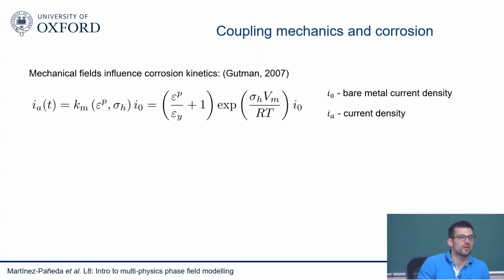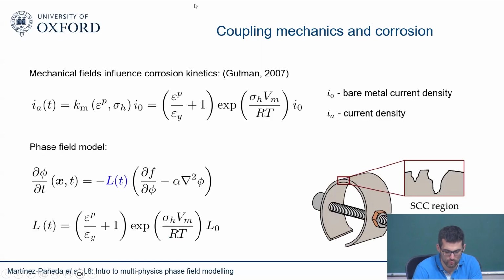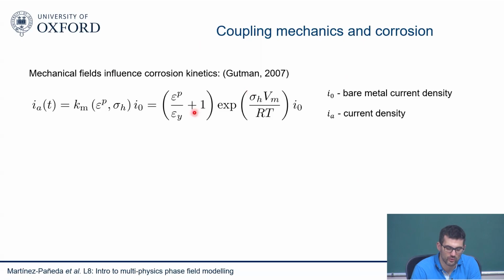But the idea is that corrosion kinetics are enhanced due to mechanical fields. And this is something that people have observed for a long time. And that Gutman, in his book in 2007, he wrote a book on mechanochemistry. He speaks on how, based on thermodynamics, the way these things change is by this. So you have a corrosion current density that relies on some sort of mechanics enhancement term that depends on plastic strain, which is, I guess, accounting for dislocation phenomena, for the way the dislocations interact with corrosion kinetics, and then some term that depends on the hydrostatic stress that is telling you how, as you expand your lattice, corrosion kinetics are accelerated.